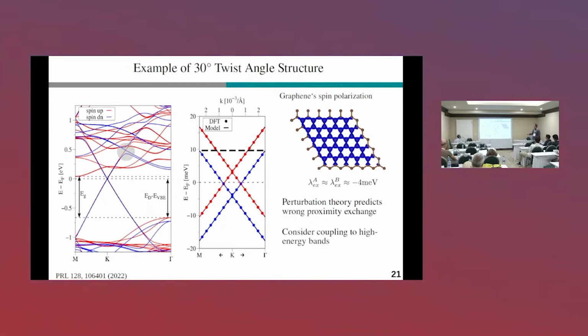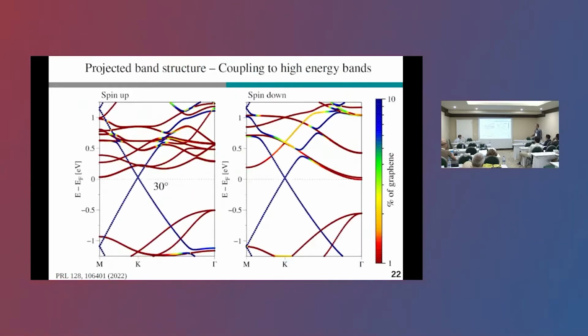Yeah, so the coupling is here. And another way to look into this is within the framework of the projected band structure. So this is again the full dispersion, but now decomposed into spin up and spin down manifolds. And the color code tells you something about the percentage of graphene within these states. So blue color means it's pure graphene, red color means it is substrate, and these rainbow colors indicate the coupling.